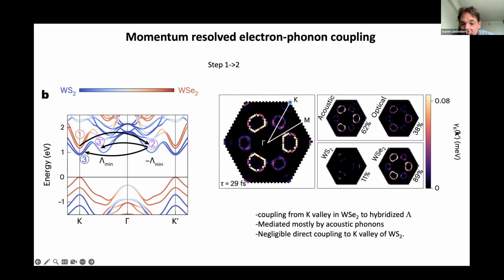You can also, through these calculations, decompose the contributions of which phonons are contributing. And interestingly enough, the calculations indicate that it's the acoustic modes that play the dominant role in enabling this coupling. Normally, when you think about hot carrier relaxation in semiconductors, it's almost always thought of as the optical modes playing the key role in mediating hot carrier relaxation. But here it looks like it's the acoustic modes that contribute most strongly to the coupling to this lambda valley. And you can also see from these calculations that there's really negligible direct coupling to the K valley of WS2. So that's the first step.